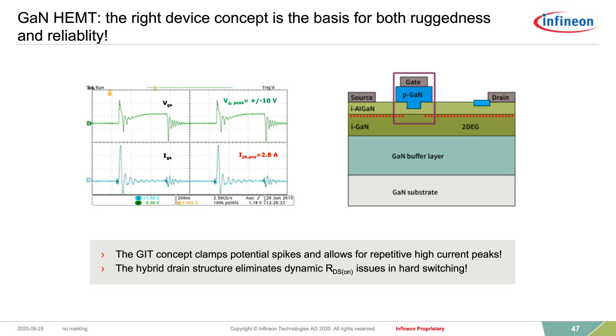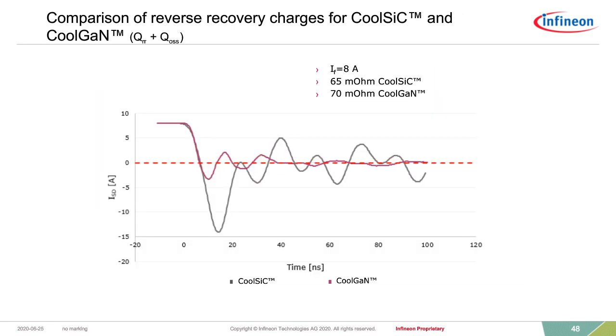A bit more specific, comparing now in a totem pole a silicon carbide MOSFET with GaN. GaN has true zero reverse recovery charge. There is no PN junction which can inject. Silicon carbide has a blocking PN junction. The ambipolar lifetime is very short, so the reverse recovery charge of silicon carbide is low, but it's not zero. As you see on this chart, the reverse recovery charge in silicon carbide is a little bit higher. Basically, what you see in both devices is the Qoss charge combined with the reverse recovery charge, and here, clearly, gallium nitride is ahead.